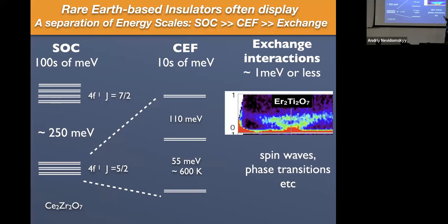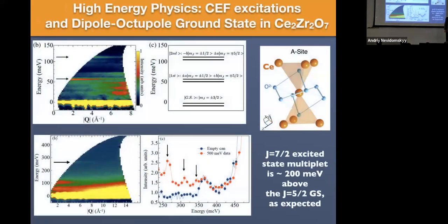And then finally, we get to the level of the exchange interactions between the magnetic moments. This is really where conventional condensed matter physics kicks in, right? It's hard to get people in my field very interested in this, but we have to do it. But this is what they're really interested in because this determines phase behavior, elementary excitations, and so forth. But this is a much lower energy scale. This is like 1 meV, and I'll just show you some spin wave measurements from one of the other rare earth pyrochlores that we've studied, erbium titanate. So at any rate, if we're going to do meaningful spectroscopy on this system, we've got to do it on all these different energy scales in order to understand things properly. And so that's what I'm going to show you.